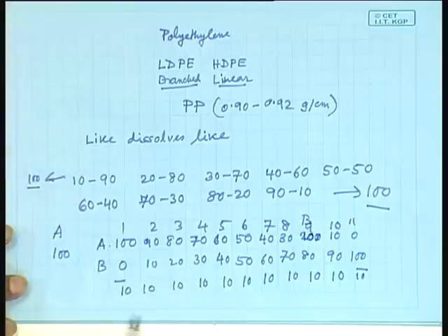You will find certain fractions of solid has come out, and you filter it, wash it, and by gravimetric means you get the fractions of those solids you have got. Then you plot those fractions. Then with the help of other techniques, once you have got a certain quantity of one fraction, you measure its molecular weight by some absolute techniques. After measuring the molecular weight, you have data of different fractions, say 11 fractions or 10 fractions, of different molecular weight.